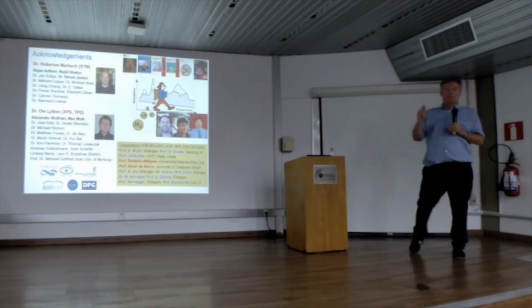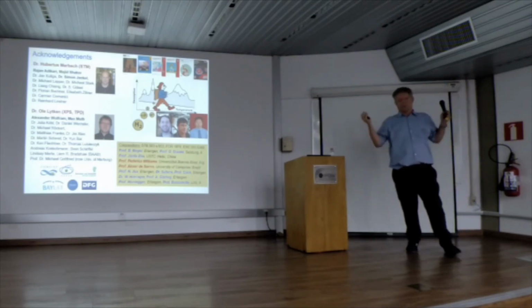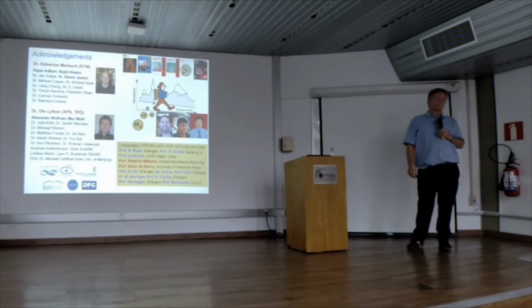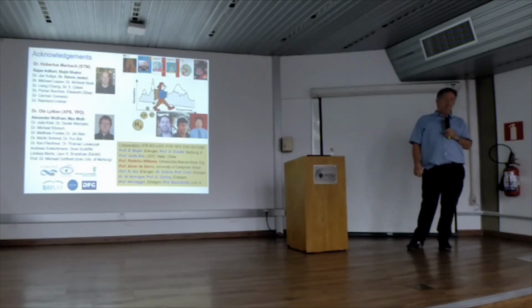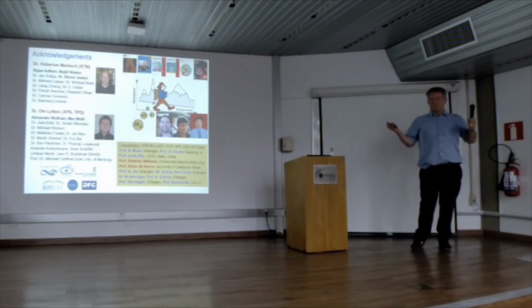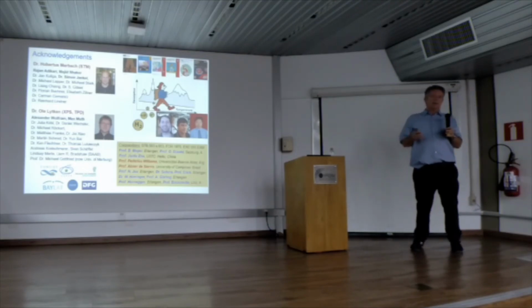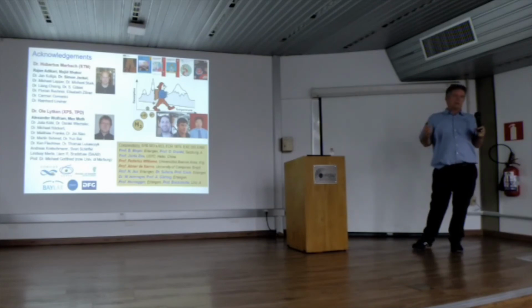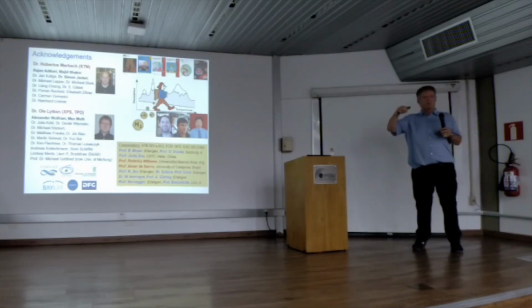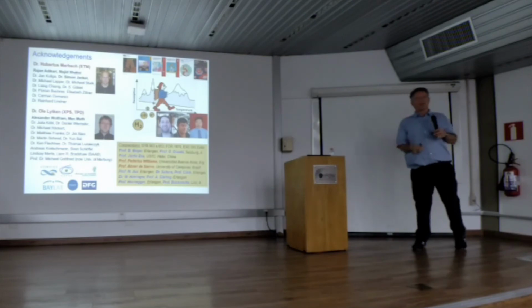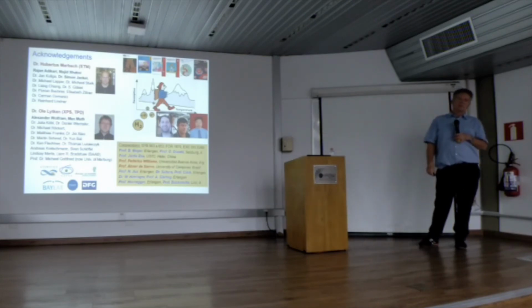And this happens if you have a metal atom in, then they're so fast that you don't see. Exactly. The super fast ones you simply cannot image, because while you are scanning, they are moving around. Then you see fuzzy images. But sometimes you catch one under the tip moving for a slow distance, then it goes away again. You have fuzzy, big images.